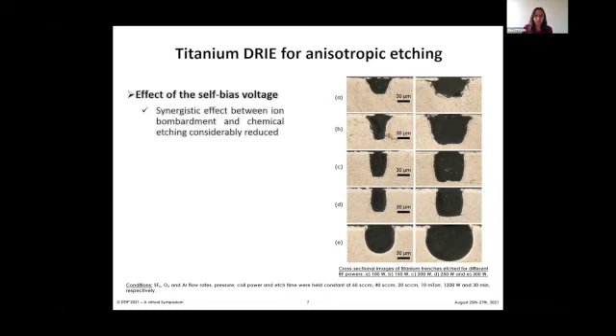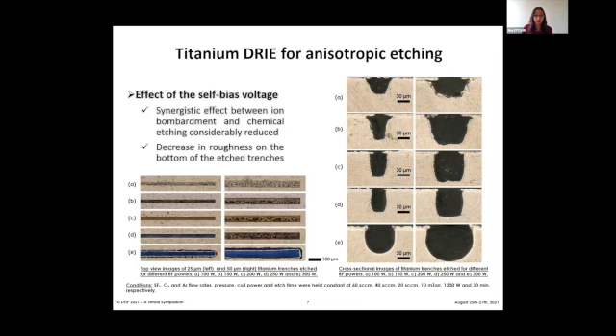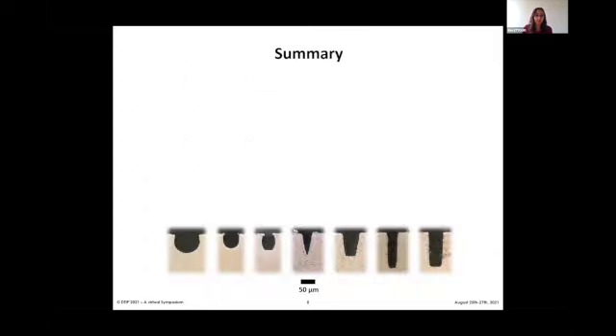It is also consistent to observe, as shown in the second figure, a decrease in roughness on the bottom of the etch trenches as the self-bias voltage increases. However, it should be noted that the variations are synergetic with temperature, and care should be taken in interpretation.